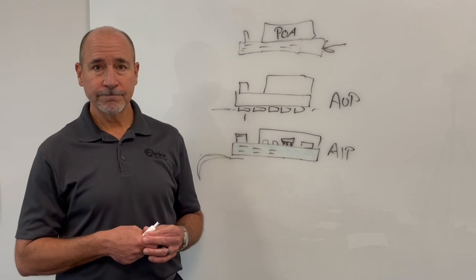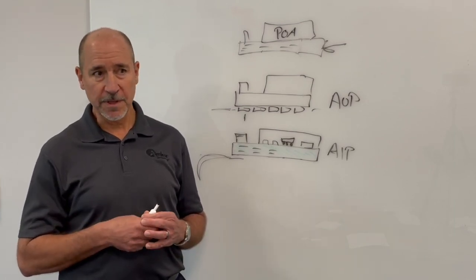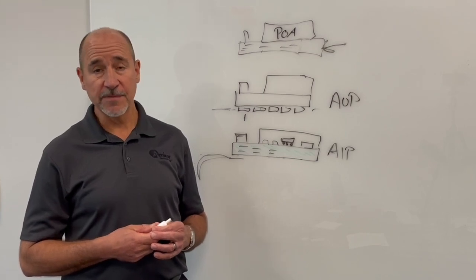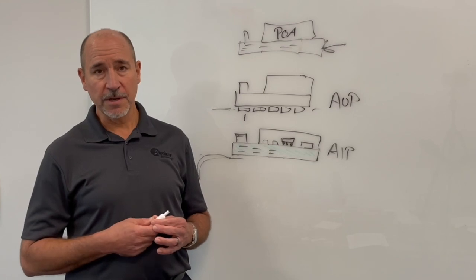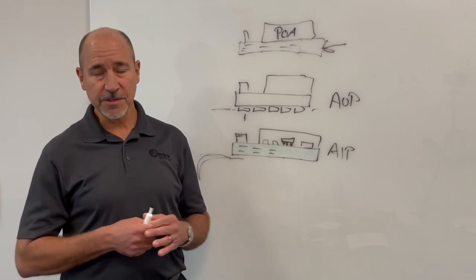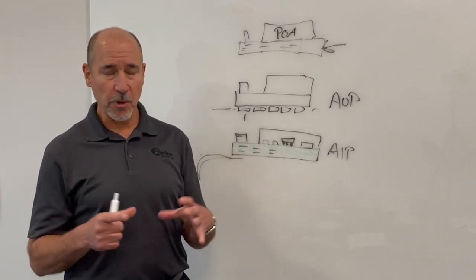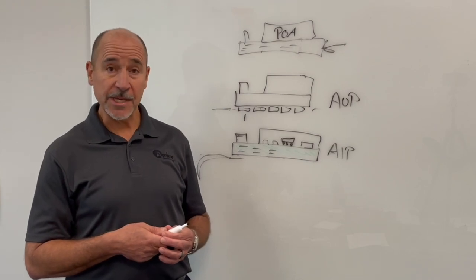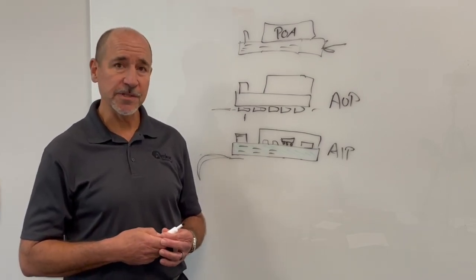What are the advantages of glass is it does have the same coefficient of thermal expansion as silicon, right? Very close. Yeah, very well matches a lot of the silicon and more of the stiffer materials that we deal with in semiconductor industry. So the CTE mismatches are addressed with glass compared to the organic core, so that's a very big advantage. Also, of course, the electrical characteristics and properties, and also the fine feature sizes that one can produce on glass using some of even the more traditional RDL-type technologies. So glass has the ability to also have very highly integrated and fine distribution of signaling on the substrate itself. So it's very distinct advantages. I think we're also accustomed to dealing with organic laminates. We drill in our strips, we drill tooling holes, and the tooling holes are used to push the substrate through our assembly process. Now with glass, we have to come up with either carriers or some techniques to provide these extra features that accommodate a high volume manufacturing process. So that's some of the challenges I think the industry is facing now.